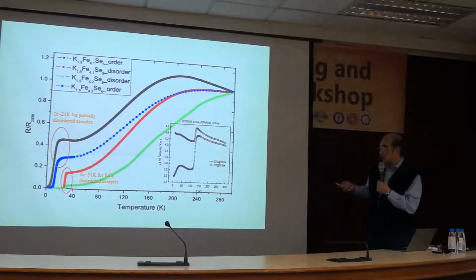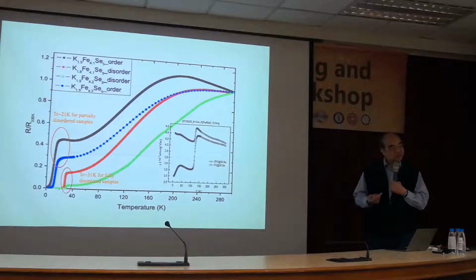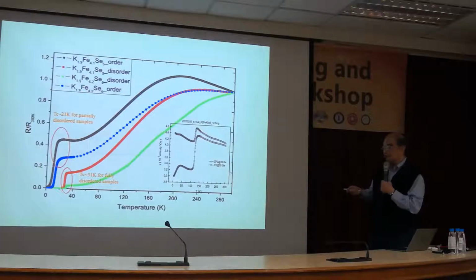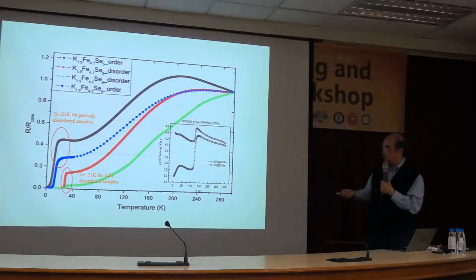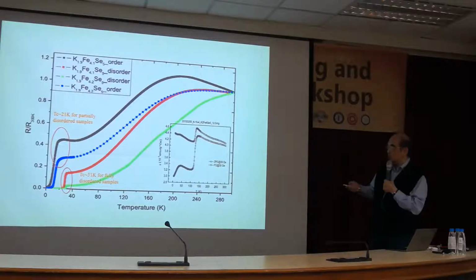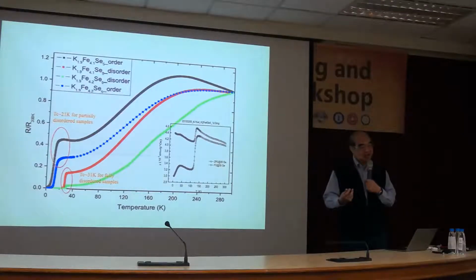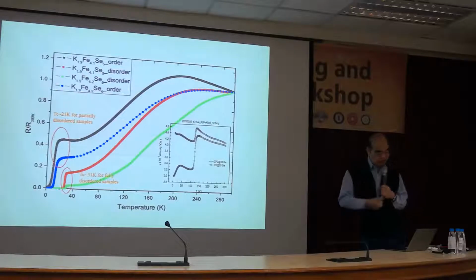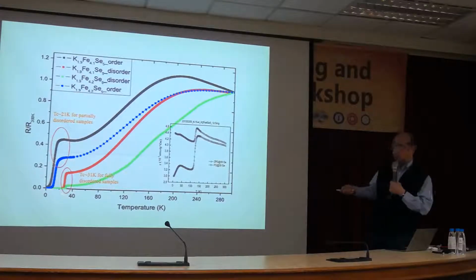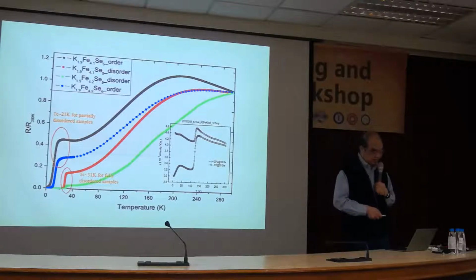Then the RT curve gives you a very different result. And the superconducting transition is very different. It has a 10 degree difference in superconducting transition. Okay, so this is the perfect, very well disordered sample. We have a 31K. A less disordered sample gets a 21K. So the competition of these two, the metallic and the semiconducting portions, essentially will determine the superconducting pairing. Okay.